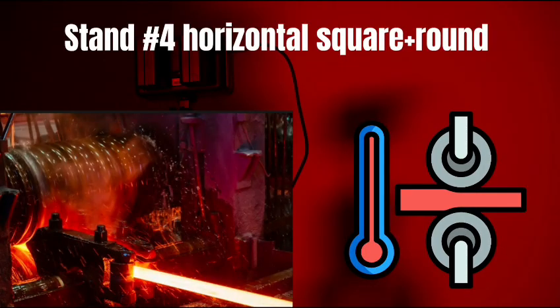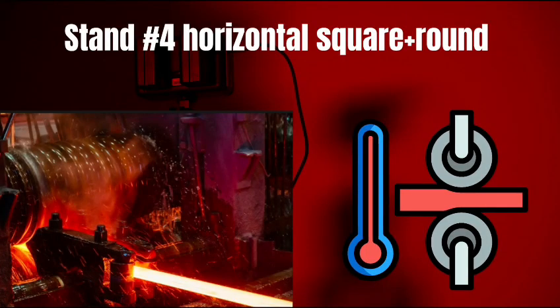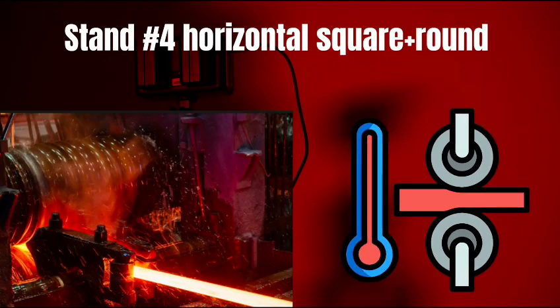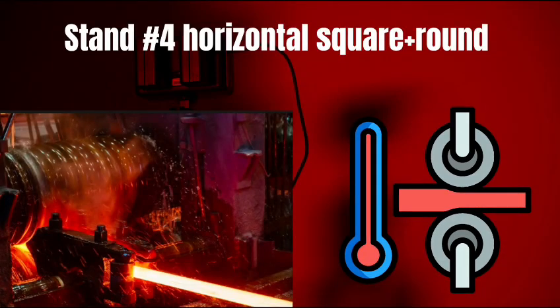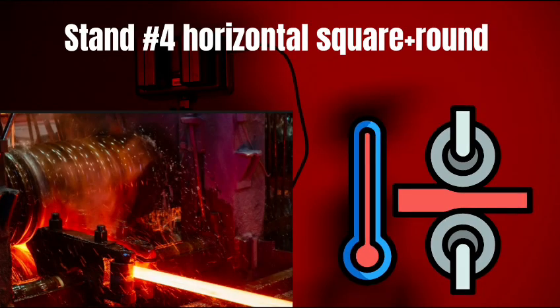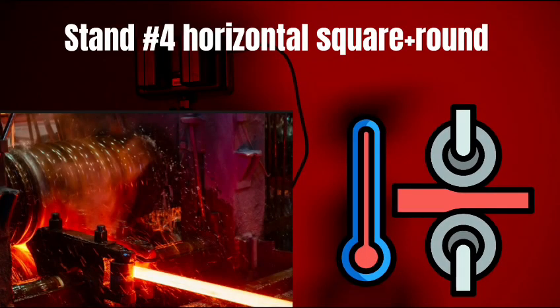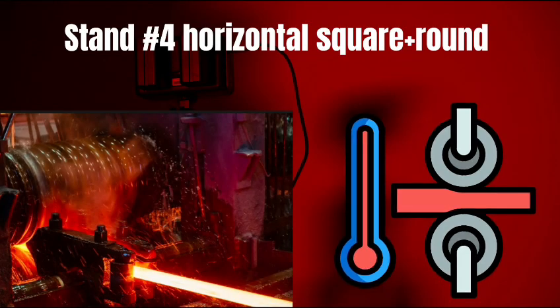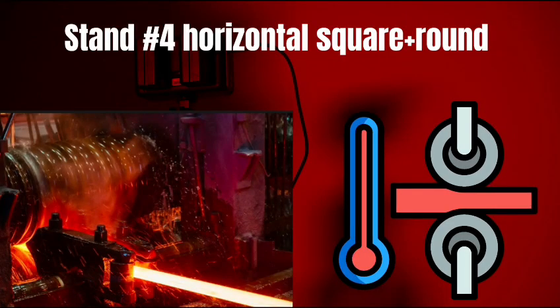Stand number 4 is a horizontal stand. The billet passes through the horizontal rollers, both rotating in opposite directions. The hot billet passes through the center groove of the rollers. Because of the rotation, the rollers grip and pull the billet forward. The billet size reduces from 80 mm to 65 mm, a reduction of 15 mm. The force is applied by the top and bottom. The billet shape is square plus round.